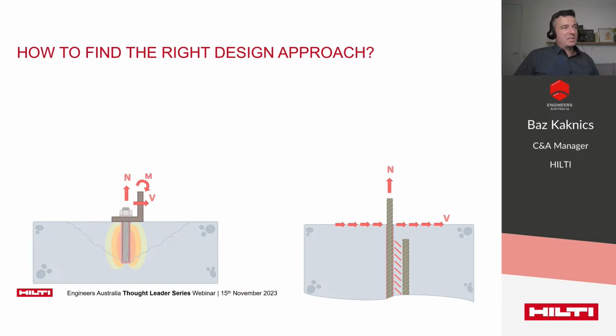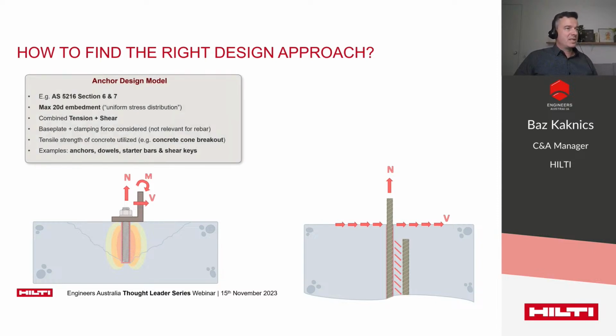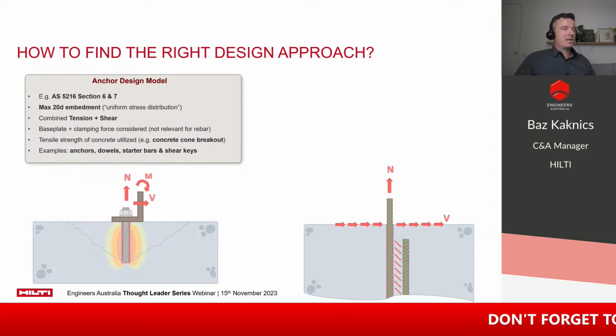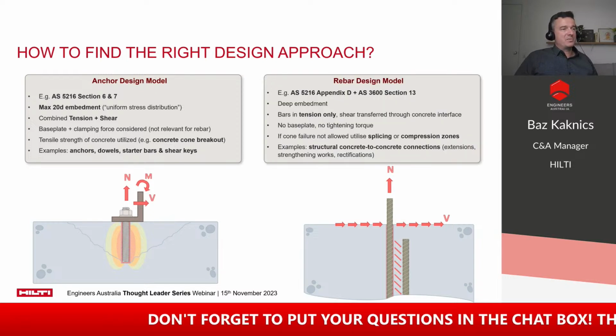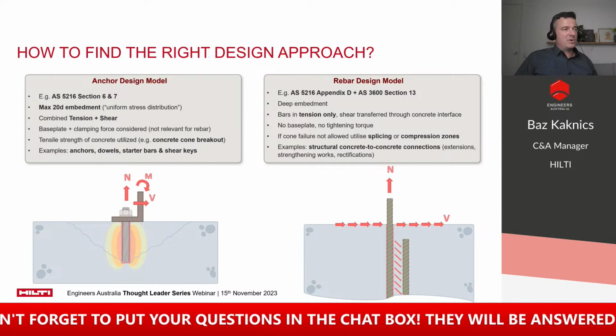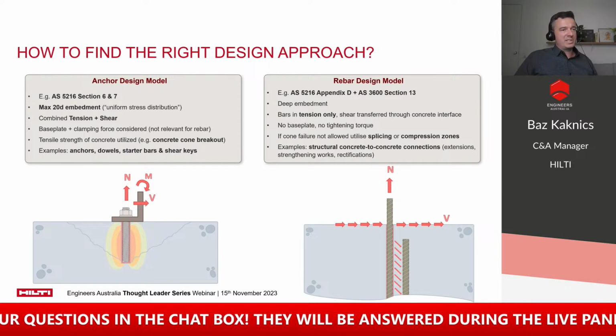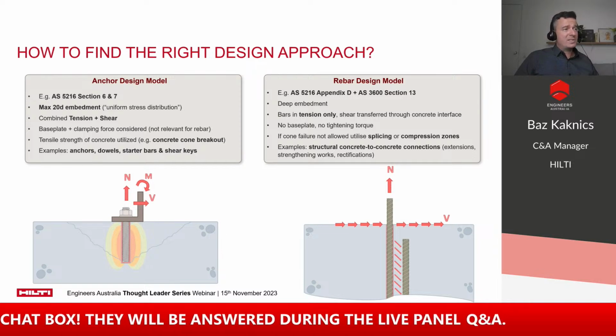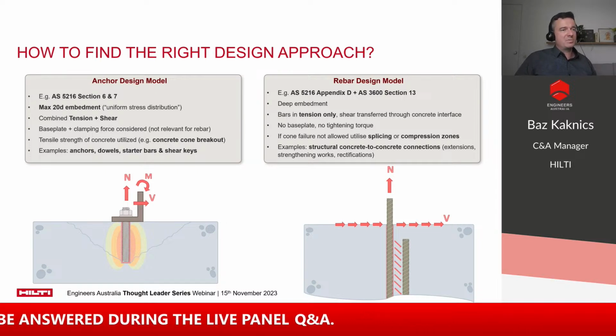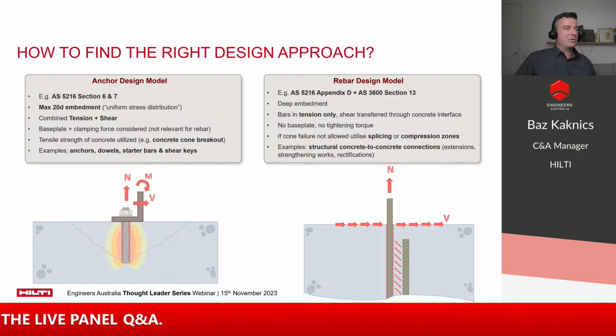In summary, the main goal of my presentation today was to help understand the differences between the anchor and rebar design theories. In certain cases, rebars may be designed based on the principles of anchor theory, for example, when they are used as shear keys or dowels, and the embedment depth is not greater than 20D, as we discussed earlier. Designers might also use this design method for shallow embedded starter bars, where concrete cone failure is expected and therefore must be accounted for. For the more traditional applications of post-installed rebar, however, the specifically developed rebar design methods should be utilized. These are suitable and safe to be used for deeper embedment depth, but the bars must only take tension forces, and the shear force must be transferred by different ways, for example, by roughening the concrete interface.